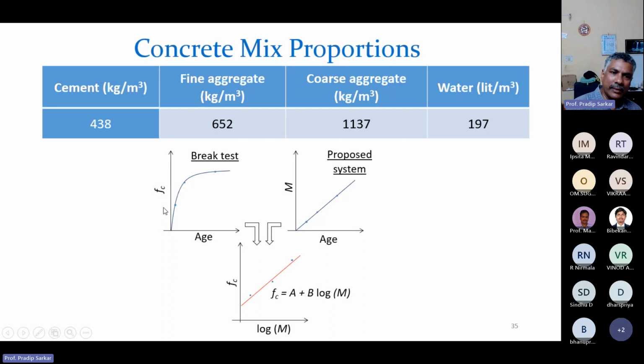We did break tests at different ages, and we got this strength. So the f_c versus age relationship, and maturity and age, were also calculated in the laboratory. Then this maturity versus strength are correlated, and the A and B values are evaluated.